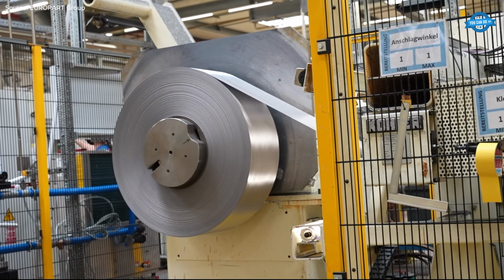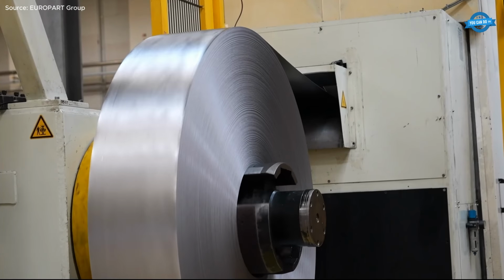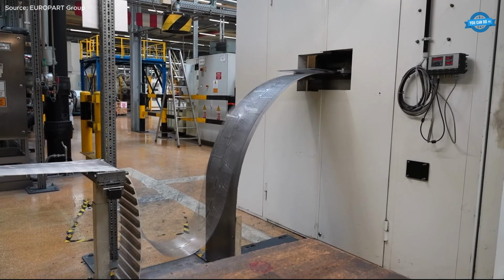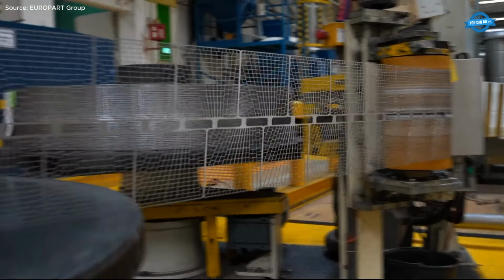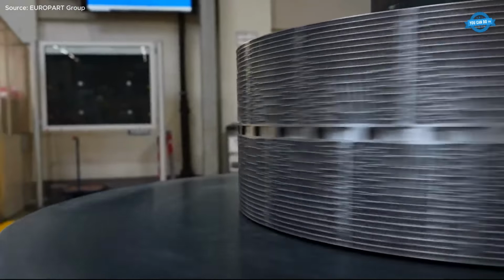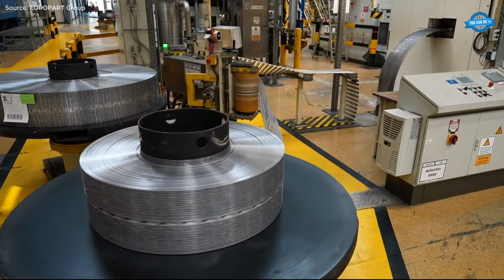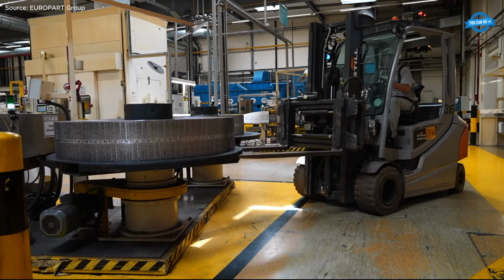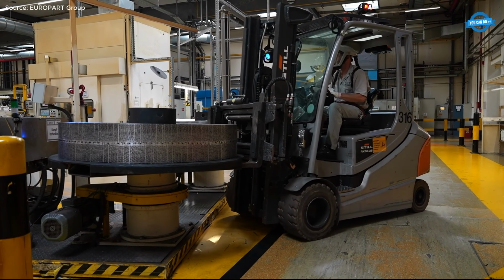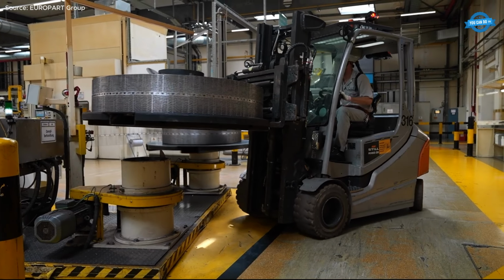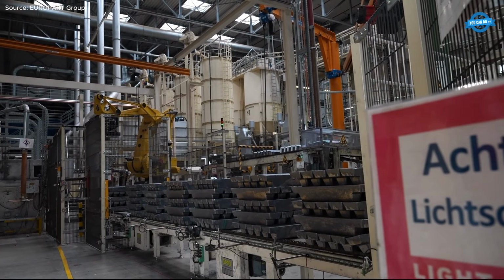The tour starts with the core raw material, lead. VARTA uses 350 to 400 tons of recycled lead per day, contributing to the battery's exceptional recyclability rate of over 98%. After melting, the metal is cast into strips, rolled to 1 mm thickness, and stamped at high speed to form precision grid plates.